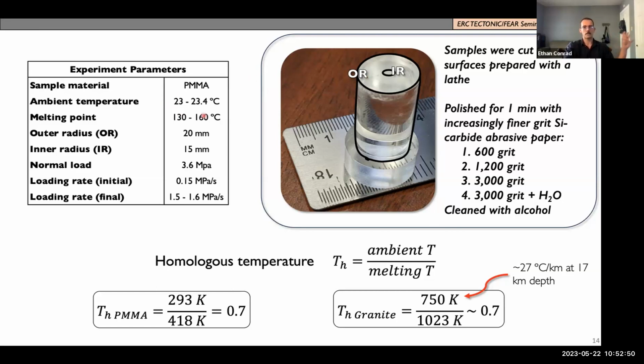Some other key points is that its melting point is between 130 and 160 C, so really attainable at standard temperature and pressure conditions. We're using a normal load of 3.6 megapascal, and then we're changing the loading rate. We're going to think about this methodology more, but we change the loading rate from an initial 0.15 megapascal per second to a higher loading rate later of 1.5 to 1.6.